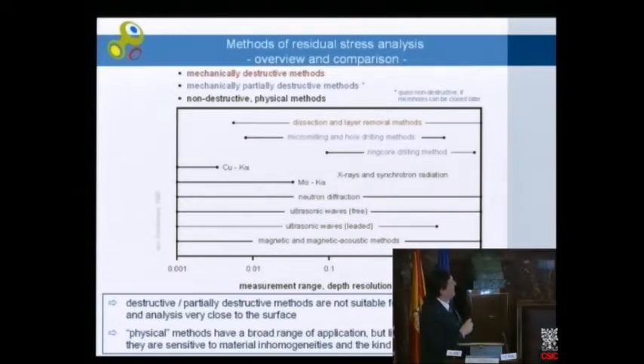and depth resolution ability. And so we can see that in the case of this type of coatings, varying from 10 micron to maybe 500 micron, this quasi-non-destructive technique, what we call the micro-hole milling and drilling method, is a quite appropriate one, and we try to combine it with X-ray analysis and also with magnetoacoustic analytic tools.